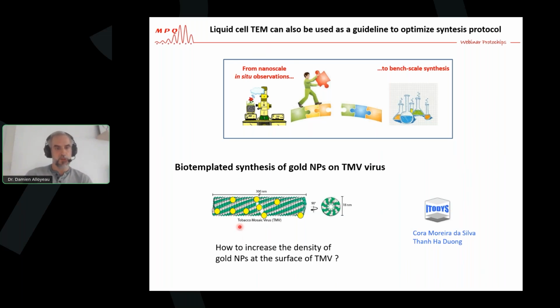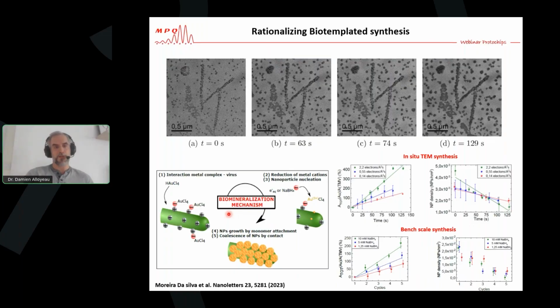And the key for this is to obtain a very high density of small nanoparticles at the surface of the TMV virus. So the only question we wanted to answer here is how to increase the density. So we designed this in situ experiment, and we see that we can follow the growth of nanoparticles at the surface of those viruses. We see that the density of nanoparticles is much higher at the surface of the viruses, which confirms that there is a strong interaction of the negatively charged chloroauric acid with the positive charge of the virus capsid, which induces the nucleation of nanoparticles at the surface and their growth.